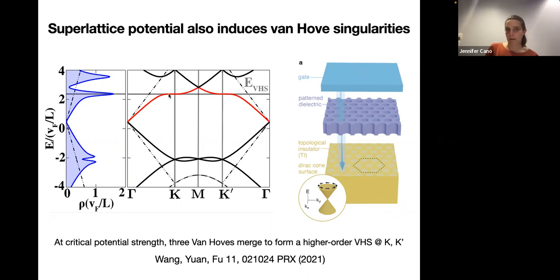There's this flat spot, and that flat spot is a Van Hove singularity, and it leads to a pileup of the number of electron states. And so this plot on the left is plotting density of states as a function of energy. And so you see that there's a peak in the density of states exactly corresponding to these flat spots in the band structure. And so this is another way that we can increase the density of states, not at zero energy, but at some higher energy.